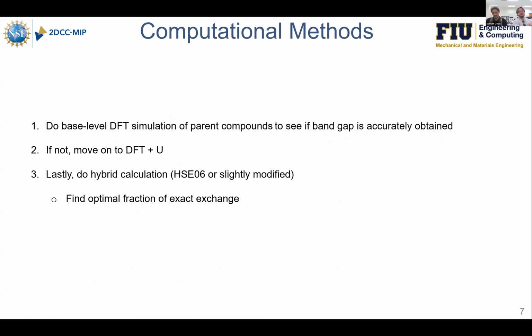So starting with the computational methods, the first thing that we did was just a base level DFT simulation, very bare bones, no special parameters on anything, just to see how the properties would match that reported in literature for the parent compounds. And then after that, we move on to DFT with a Hubbard correction, or DFT plus U for short. And this is kind of a way to empirically get physical properties, especially band gaps for the materials, while saving a bit on computational resources.